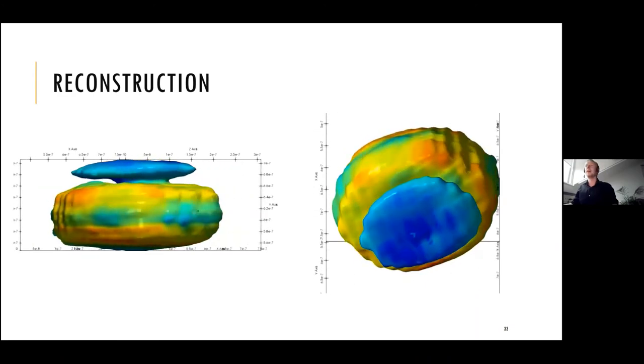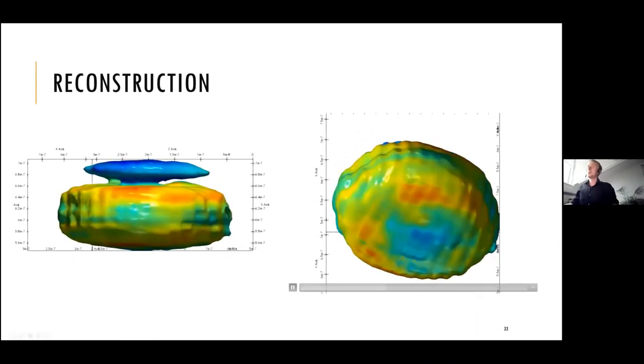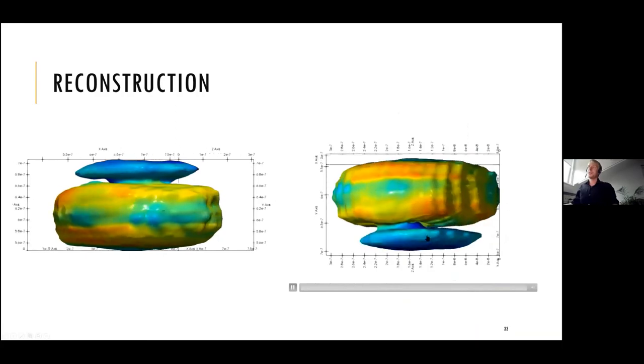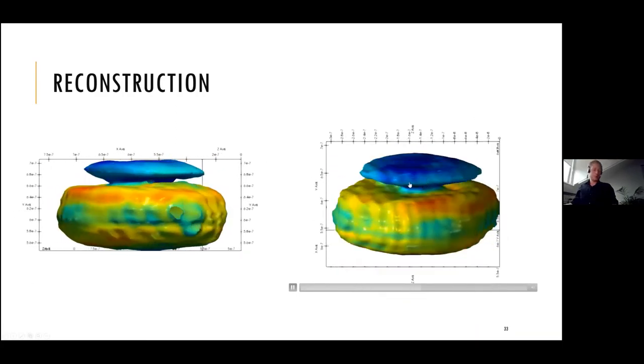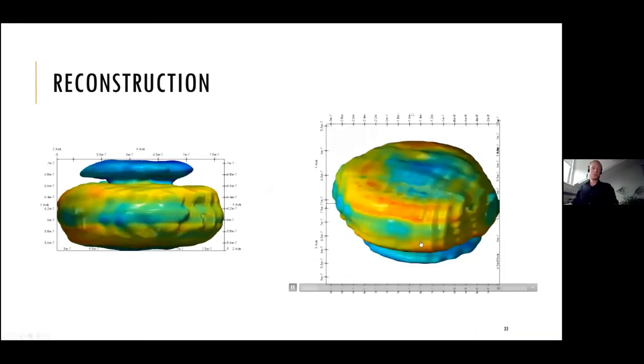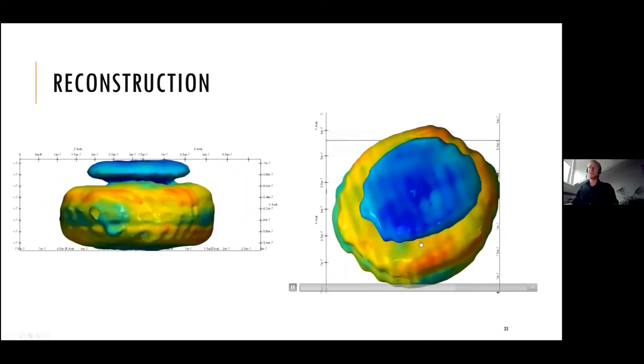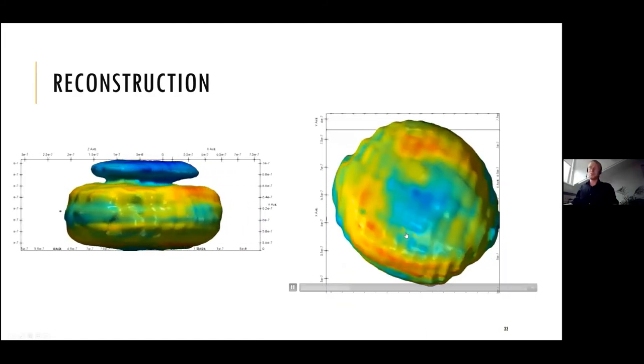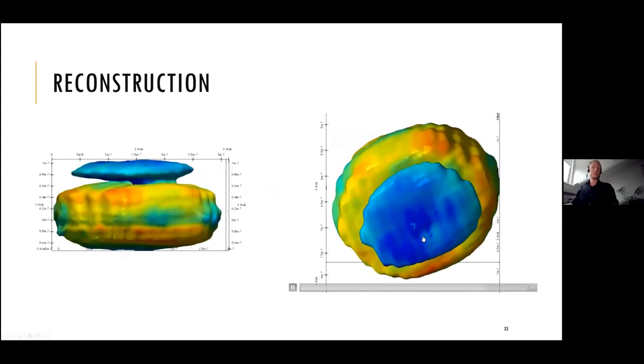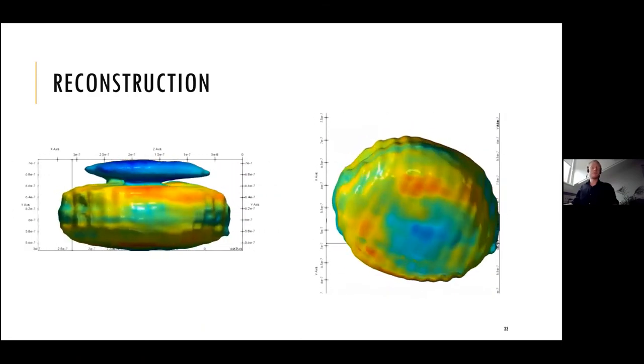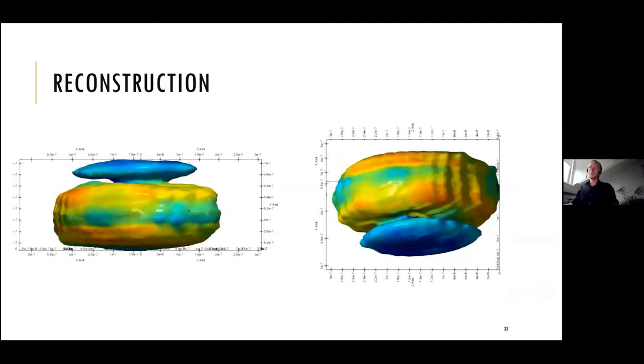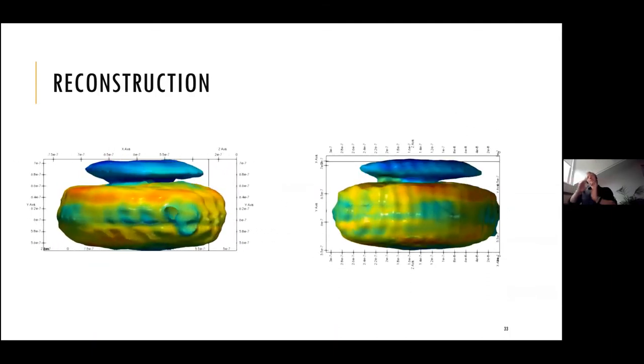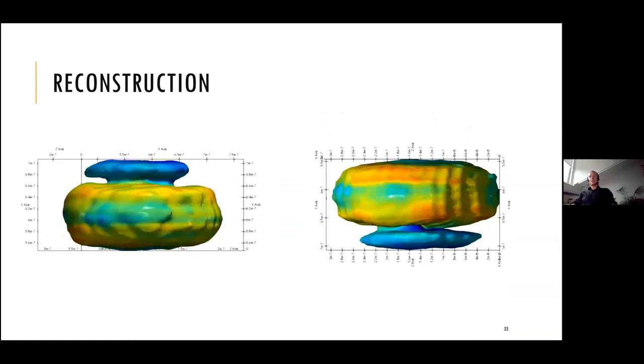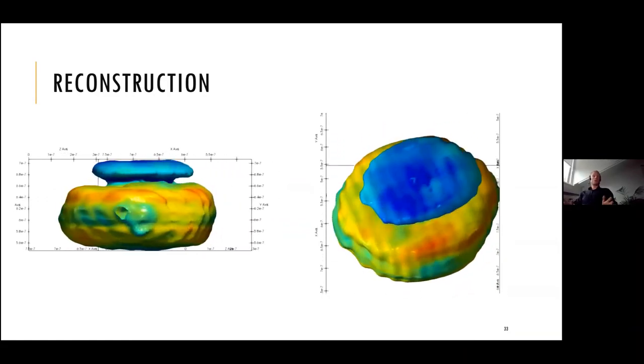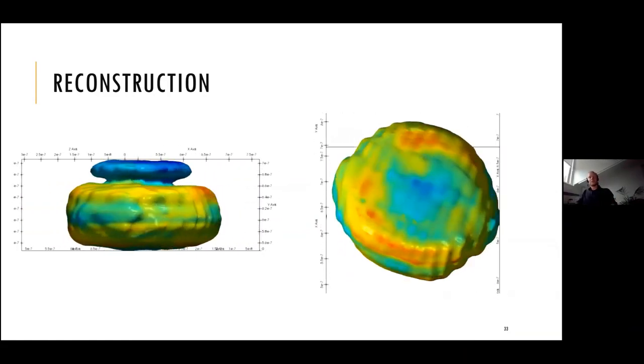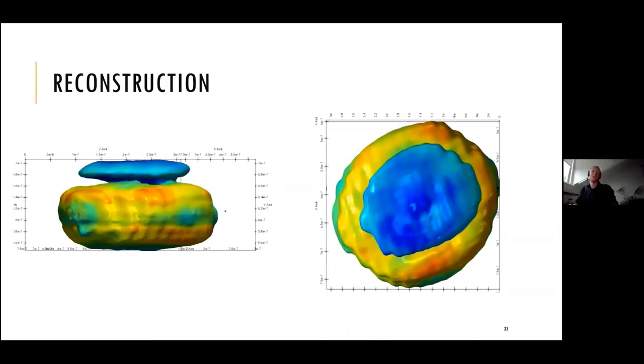and it actually looks like the gold nanoparticle we measured. And already here, you can notice one of the interesting effects we can reconstruct with Bragg CDI. You see this gap between two parts of the crystal. There's nothing wrong with the crystal itself. It's still a full particle, but we miss the intensity in between just because it's not scattering to this Bragg condition we measured, because there is a twinning defect. So basically the crystal orientation is different for this part of the crystal. This is one of the sensitivities you can achieve with Bragg CDI, which is not possible to see with electron microscopy, let's say.